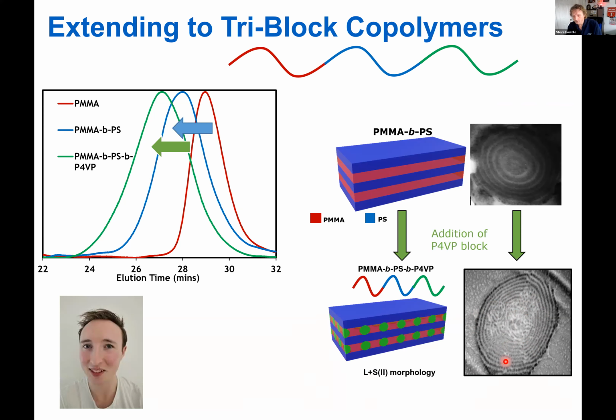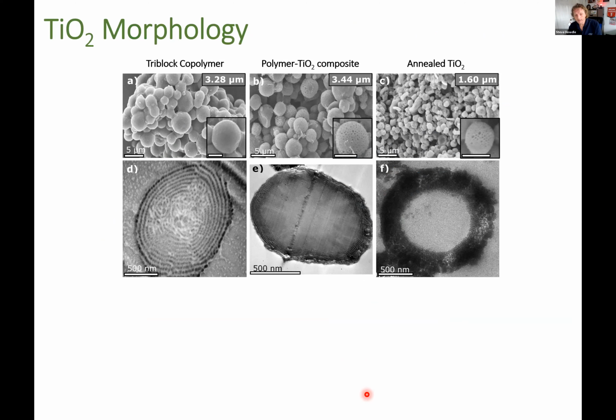It's well known that tri-block polymers show more structural variation, and we wanted to try and do this. Ryan has shown that we can actually get to looking at these tri-block copolymers. Again, he's converted these into some inorganic oxides. So here we've gone from the tri-block polymer to putting in the titania and then annealing it to create quite an interesting structure.